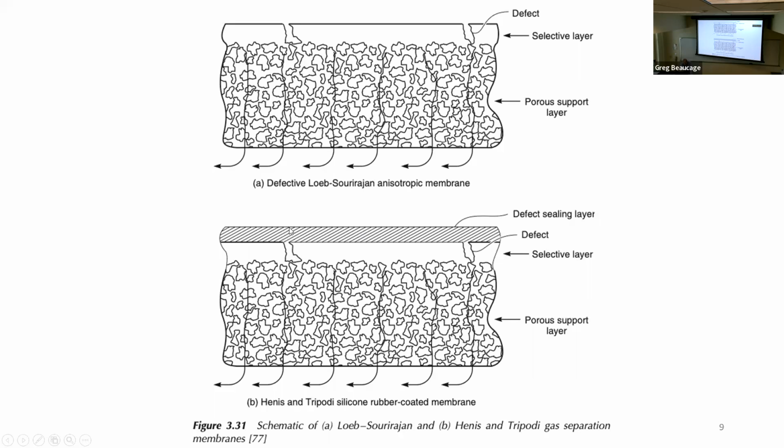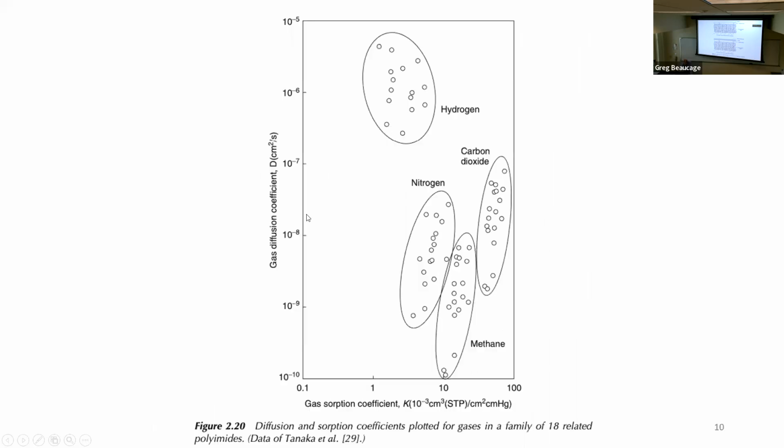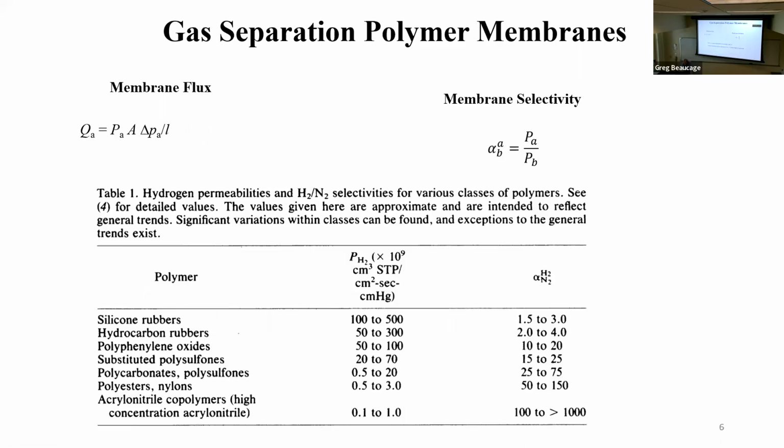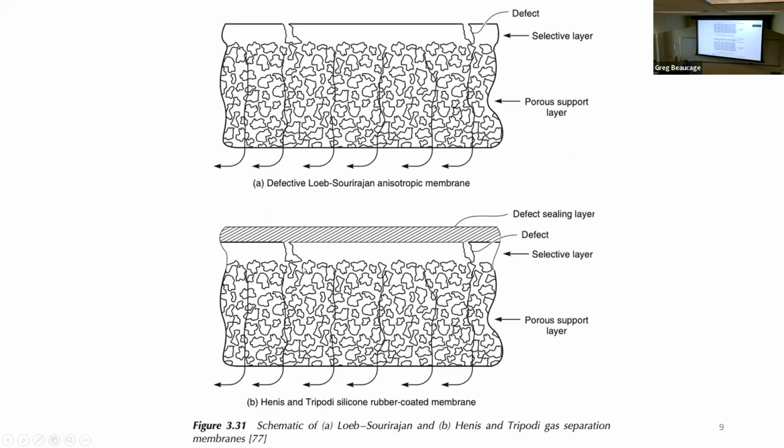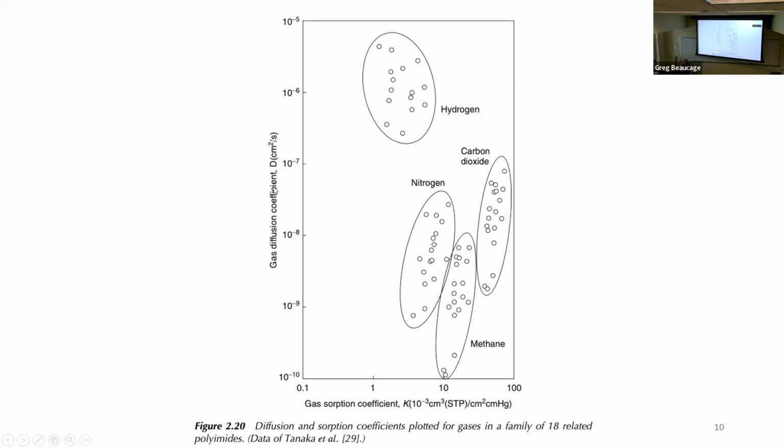So the high flux, if you get a thickness thick enough, then there can be a balance between the high flux and the separation. It's basically you wouldn't use PDMS, you'd use something in this chart that would match it out. So if you doubled the thickness, then it would be the same transport as a separation layer, and then you wouldn't need to worry about the cracks in the thin layer. Right, so that's kind of the idea. There's a balancing act between how much you can get through total and then preventing transport through these holes, which has no selection at all.